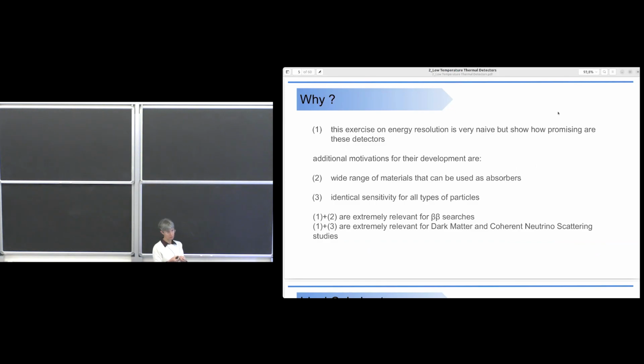And this is important for double beta decay because yesterday we discussed the following point: our future experiment has to use the source equal detector approach. So I need a detector that is itself the source of the double beta decay, and we have a list of isotopes that are candidates for double beta decay, and only a few of them are semiconductors. With some of them, it's possible to grow a scintillator, a crystal that has scintillation properties. But keep in mind that the scintillator does not have the same energy resolution as a semiconductor like germanium. And we also discussed that energy resolution is an important point.